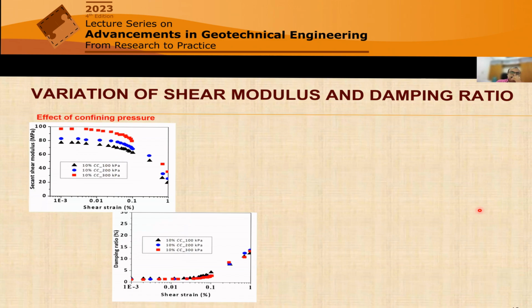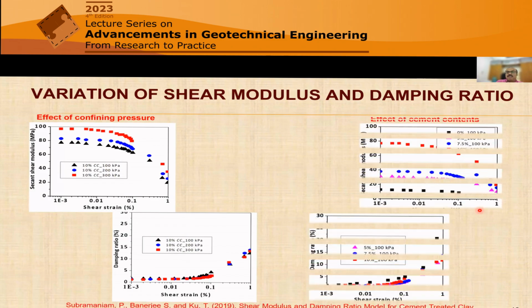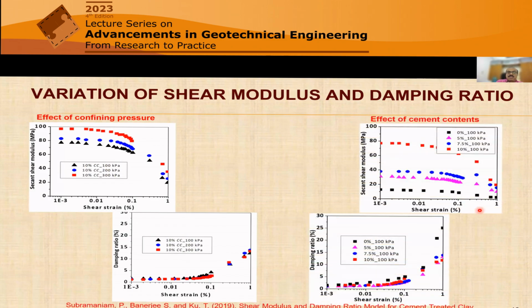Now we checked different conditions, with the effect of higher confining pressure and then higher cement contents. And as you can see, confining pressure has quite a significant effect on the modulus, but it really doesn't make much difference in the damping ratio. We can see a similar thing over the cement contents as well.